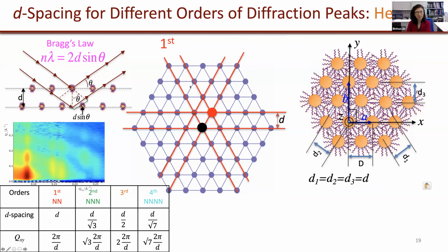We asked you the degeneracy of this peak. It corresponds to all the d spacings, with 6-fold symmetry, because this rotated 180 degrees is another symmetry. So all of those land in the same peak, and the degeneracy is 6. That's because we have polycrystals. If I have a single crystal and shine a beam, you get 6 spots. So that gives you the d spacing, and the first peak corresponding to 2 pi over d. That's the first order peak.